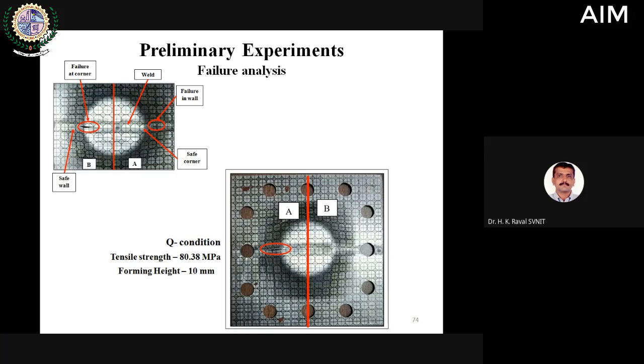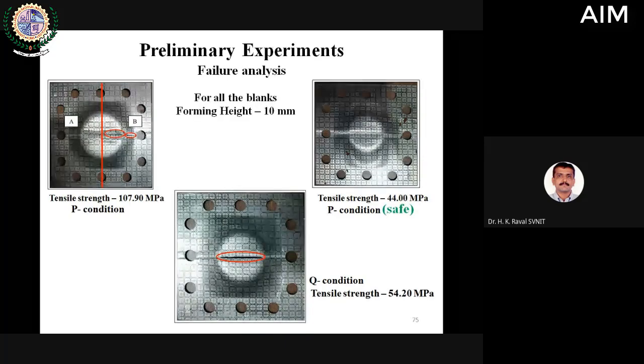This is the failure analysis. Failure is reported here. By chance, if you can track the cursor, I am moving the cursor just to help you look at the failure. This is a weld line. Prior to forming, welding is done, and when forming is done, the welds open. You can see these are the open portions. The weld gets teared off. These are separated. All this is failure. It is just to indicate how failure will localize. Localized failure is observed, so this is the failure image. Again, a few more failure images are seen. Actually, this is because of the poor welding.